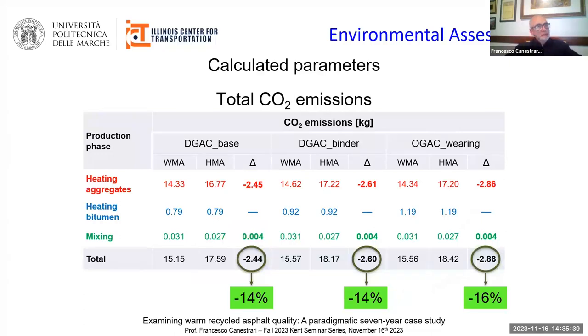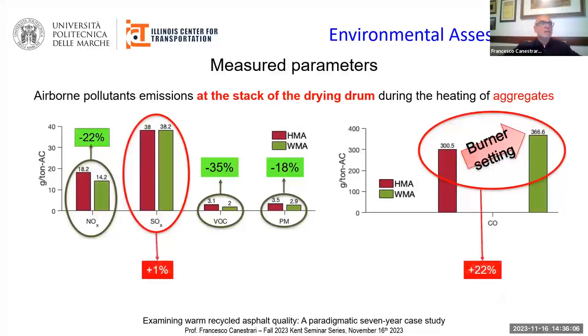In summary, based on the calculated parameters listed in this table, the total CO2 emissions for all mixtures show a reduction of more than 14%, with a peak of 16% reduction in the case of warm recycled open-graded asphalt mixtures. These results are in good agreement with the other data available in the scientific literature.